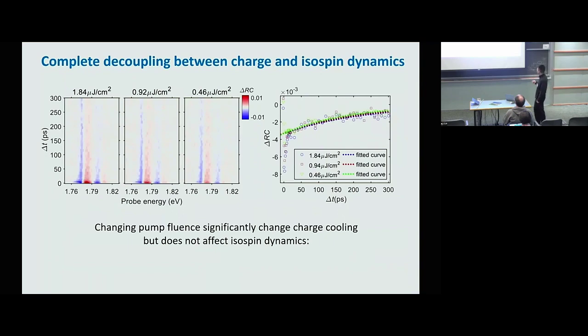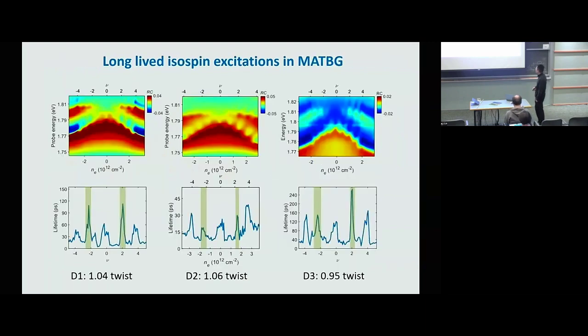So this not only tells us that these two dynamics are completely decoupled, but also it tells us that this slow component, at long time scale, actually does not depend on how we excite the system. So it also gives us intrinsic information of the system, and doesn't depend on how we excite it. Okay, so then we can take a closer look at this slow decay around plus minus 2. So I have measured 3 devices, and they are slightly different in twist angle and slightly different in the behavior. But the consistent behavior we observe is that there's a quite slow relaxation. On the electron side, it's around +2, or sometimes slightly above. But on the hole side, it's always between -3 and -2. It's well away from -2.